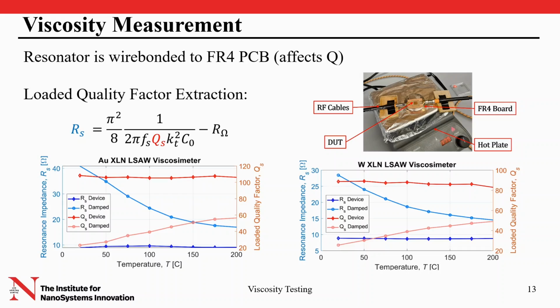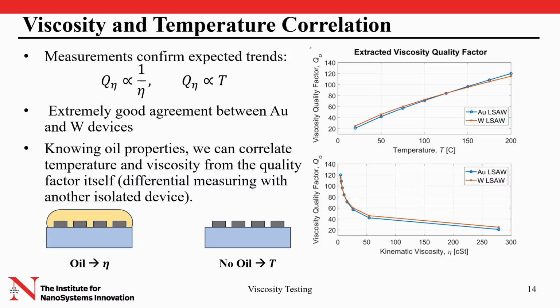Of course, all measurements were carried out over a very long time range to ensure steady state conditions. All the results were fitted through MBVD modeling, and the viscous damping and the loaded quality factor were extracted from the motional resistance of our MBVD model after de-embedding the effect of the ohmic losses, which was very small, having used gold and tungsten, which have very low resistivity. Both plots show the relationship between the series resistance and the evaluated quality factor as a function of the temperature. Now, the only thing left is to correlate the data.